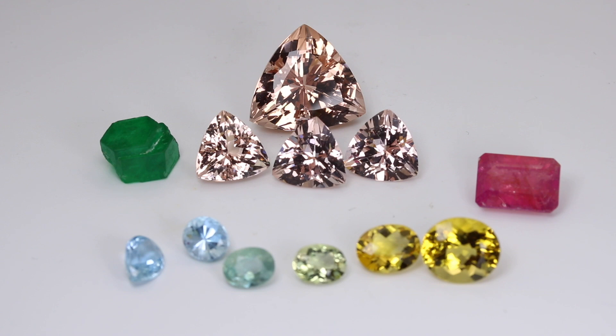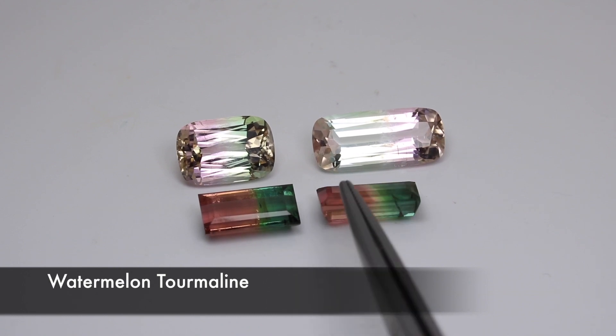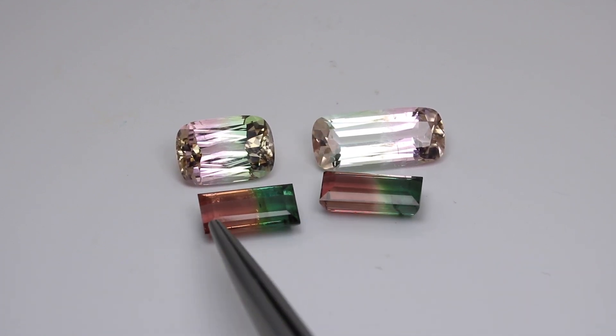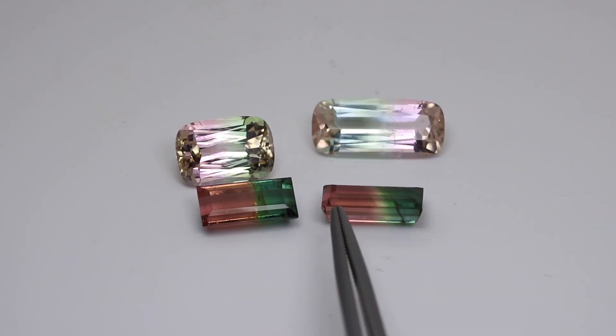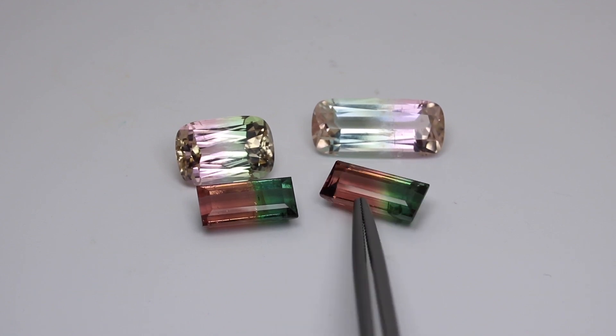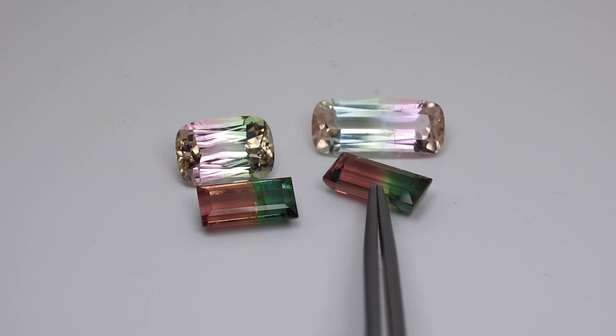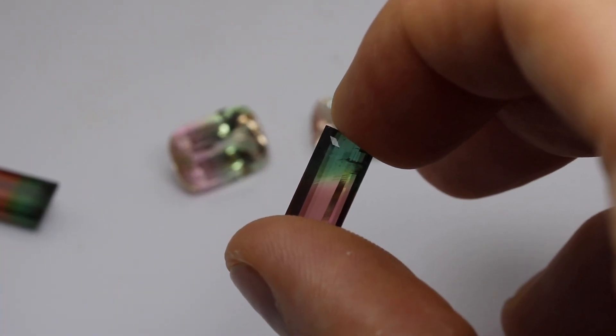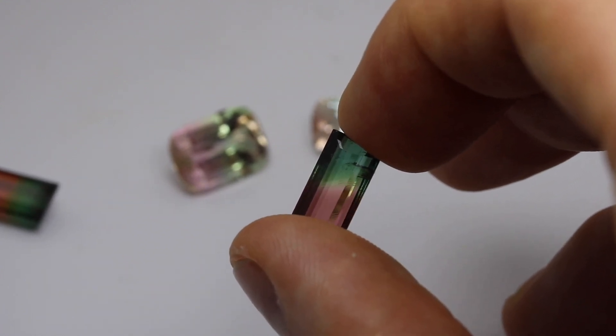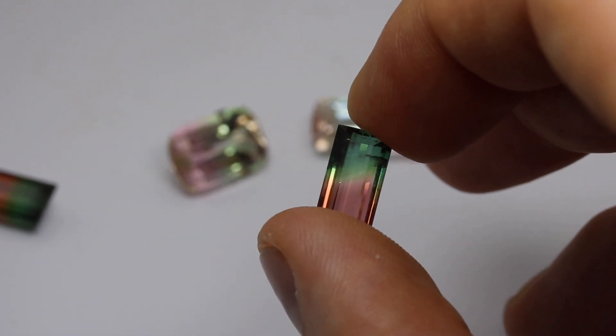The real takeaway is that some gemstones have a special name because of a color, and that color is not always an essential part of what that mineral is — it can be almost an accident, a trace element impurity. This watermelon tourmaline really helped me understand the influence that the growing environment of the crystal has on its color. You can see that one area is pinkish-red and then this part is green. When the crystal was growing it had certain nutrients available that created the reddish area, and then at a different stage it had other elements available that created the green. There's even a colorless area in the middle, showing that at one point the crystal lacked nutrients to give it any color at all.